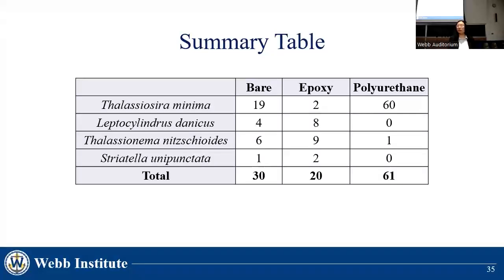The summary table above displays the amount of growth on the epoxy, polyurethane, and bare plates, regardless of their proximity to the light. The amount is demonstrated by the count of each form of microbiology, where 0 indicates no growth. It can be seen from this data that epoxy showed the lowest amount of growth overall.